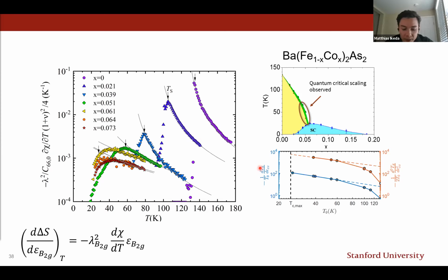So it depends. I guess it depends on what the order parameter for the phase transition really is. But if we basically think of the strain to be the primary order parameter for the phase transition, and we probe this by strain itself, then we would expect a flat temperature dependence, not a diverging one, similar to the elastoresistivity as well.